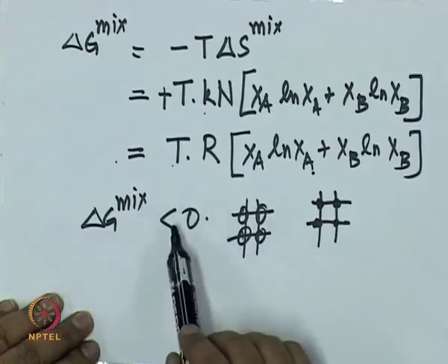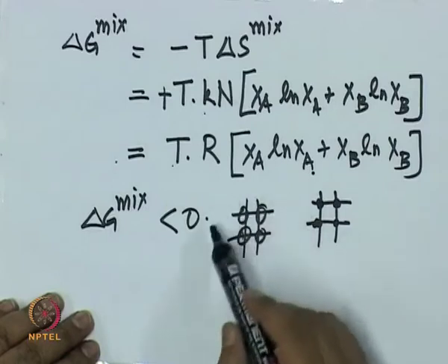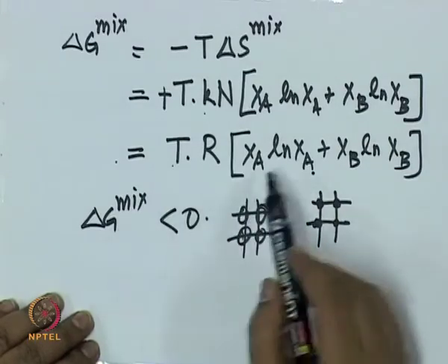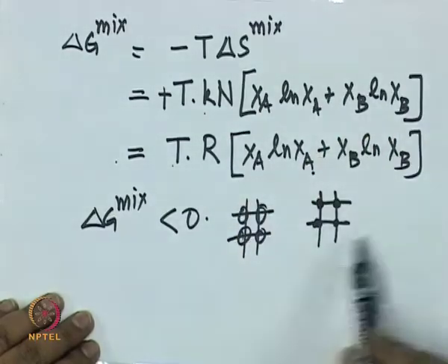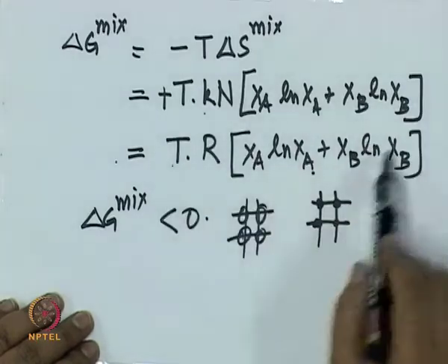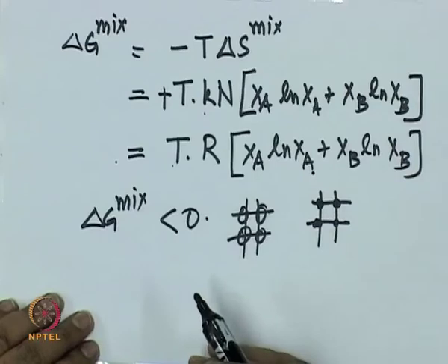That is the reason why it is called an ideal solution, because it will always mix very homogeneously; the perfect mixing, randomly arranging the A and B atoms on the given lattice, which is what we have assumed when deriving this, is the one that also has the lowest free energy.